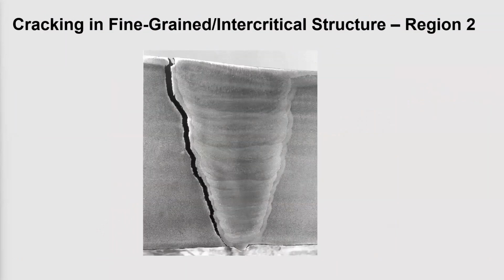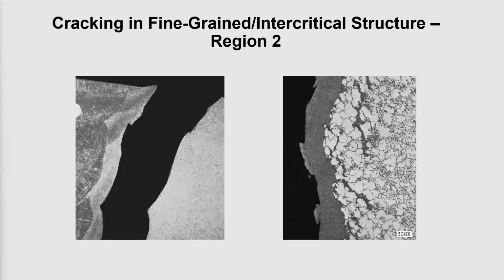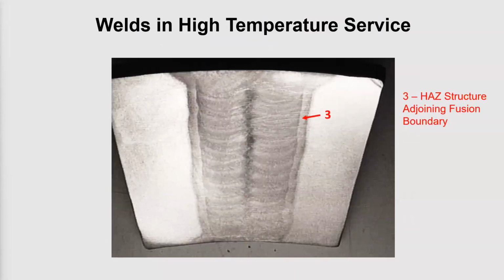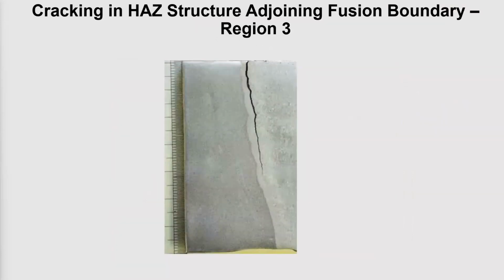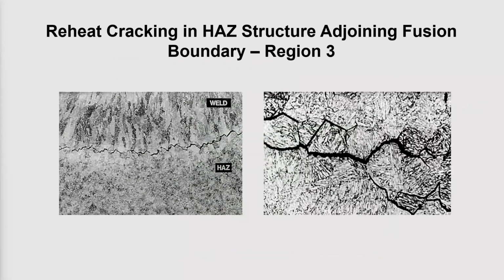I'm going to go through this a little quick. This is the typical type 4 damage at the outer edge of the heat affected zone. There have been many examples of failures related to this type of damage. The damage in the heat affected zone structure adjoining the fusion boundary. There are several different reasons that you can have damage in this area, one of which is the potential for reheat cracking in the coarse grain heat affected zone, which has very high creep strength, but very limited rupture ductility.